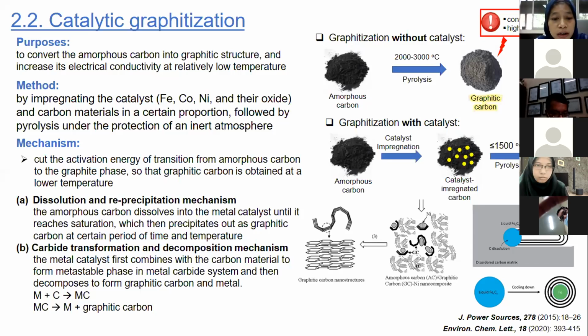At present, there are two mechanisms of catalytic graphitization. The first one is the dissolution and reprecipitation mechanism, and the second is the carbide transformation and decomposition mechanism. For the dissolution and reprecipitation mechanism, under the action of the graphitization catalyst, the chemical bonds between the carbon atoms are broken, and then the catalyst continuously dissolves the amorphous carbon until it reaches saturation. The energy level of saturated carbon is higher, so it needs to be converted to a low-level graphite crystal state, thereby obtaining a graphitic carbon material.